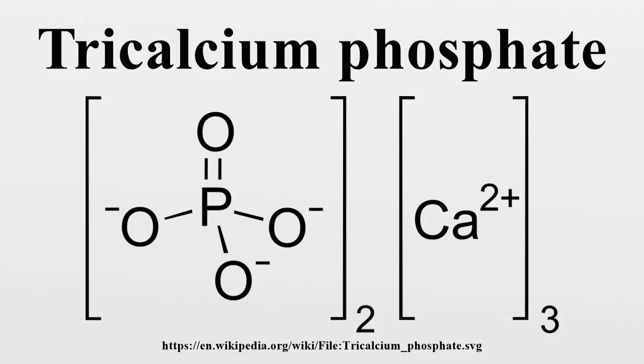Beta-TCP is bioresorbable. The biodegradation of BCP involves faster dissolution of the beta-TCP phase followed by elimination of HA crystals. Beta-TCP does not dissolve in body fluids at physiological pH levels; dissolution requires cell activity producing acidic pH.